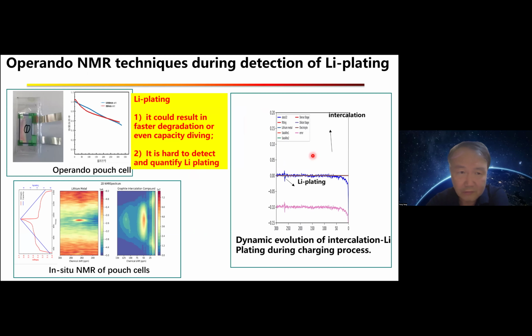We also explored solid-state NMR techniques to follow the intercalation of the lithium ion into the graphite, including as the intercalation of lithium ion in the graphite increases, the different stages of this graphite can be seen, then we also see some lithium plating. Lithium plating could cause faster degradation and even capacity diving.